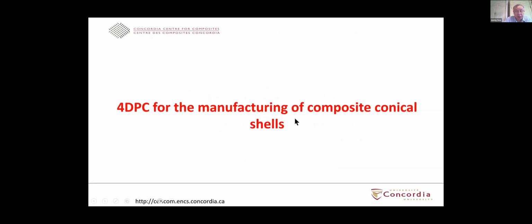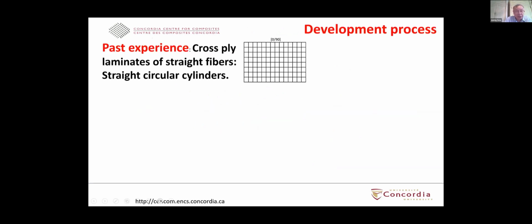Going to the topic of making the conical composite shell, we have to make the conical shell using the technique of 4D printing of composite. In this case, we use the experience that we have from the past. In the past, what we have done is that we lay down straight fibers in 0 and 90 degree orientation. Then by the time you finish curing and cooling to room temperature, you obtain this cylinder. So by using straight fibers, you have a cylinder.